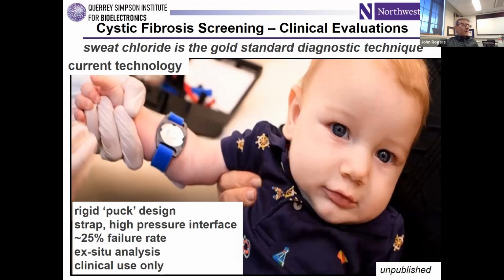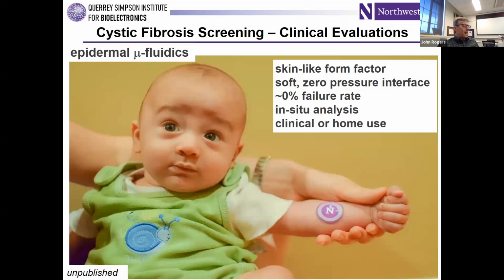So failure rates associated with leakage of sweat around this kind of puck-based device. And they asked us if we could build one of our soft skin sticker-based microfluidic devices, not only to eliminate that leakage, but also to eliminate the need for use of benchtop analytical instrumentation and separate analysis of chloride. To be able to do that in situ would greatly facilitate the test. And so we're able to put together devices with that kind of functionality. They turn out to work very well.